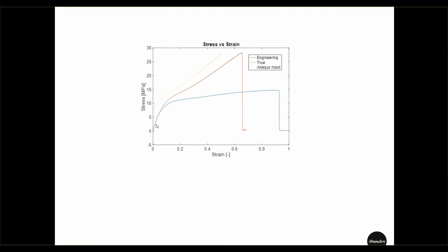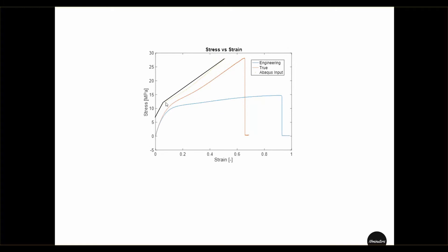Using these experimental points I have calculated these coefficients via Newton iteration. Next, I need to define the hardening for this material. The blue curve shows the engineering stress-strain curve and the orange curve shows the true stress-strain curve. From the true stress-strain curve we further construct the plastic strain versus true stress curve, shown as the dashed curve. This curve will be used to define the hardening of our BBC05 yield model, and this hardening can be used together with any other yield model.